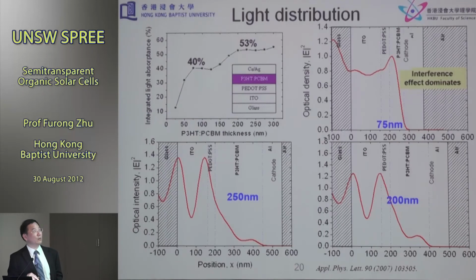If it's slightly thicker or further away, then this peak shifts either into the ITO or the PEDOT, where although the maximum light field could occur in this area, they don't generate excitons. That was the reason why. So this is probably the area we're looking at. We compared a lot of reported literature results, and experimentally, if you look into high efficiency solar cells based on this system, you will find that this agrees with the simulation very well. So this gave us some foundations.